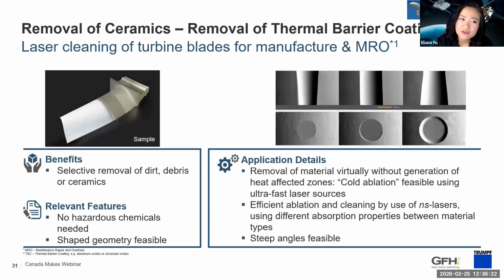So you can also think of that in the cleaning method. So going back to aerospace, cleaning turbine blades. So for example, if you want to selectively remove dirt, debris, oil, and things like that, and maybe you want to follow that with a LMD process. So you do the cleaning, then you do the deposition. So you can do that as well.